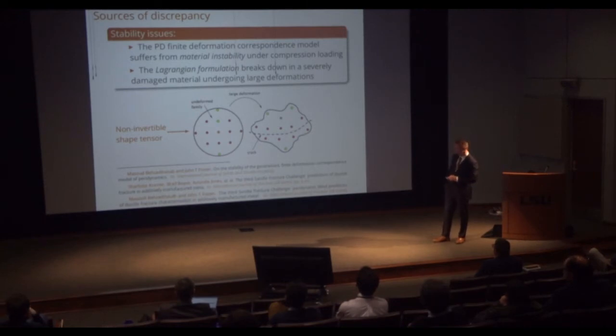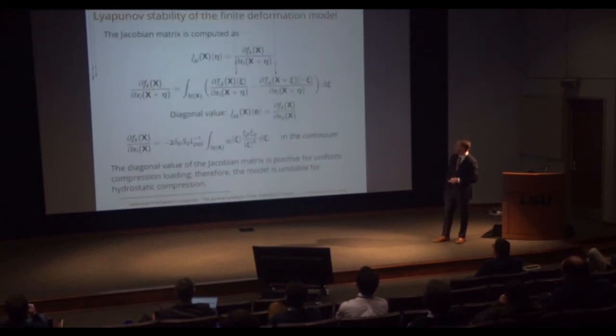And so, we did some theoretical analysis of the model itself, and we were able to prove that it's actually unstable under compression. While the majority of this problem is in tensile loading, because of the specialized geometry there are some compressive loads that occur, and that was exciting an instability in the model, and therefore was causing the issues.